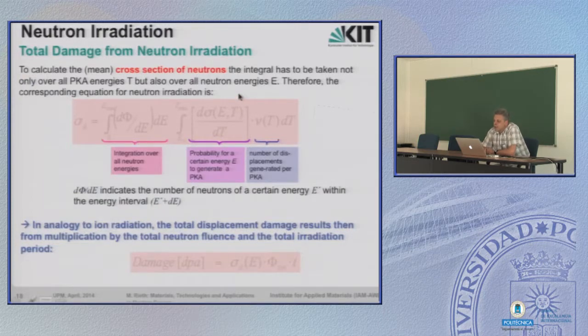It doesn't matter much for the calculation, because the cross-sections of these neutrons are calculated in the same way. We have also here the probability for a certain energy to generate a PKA. That's the same part as with the ion irradiations. Also the number of displacements generated by the primary knock-on atom. But then we additionally have to integrate over the whole energy spectrum of the neutrons. That's another cross-section given here. And in analogy to ion irradiation, this leads in the end to the same scheme for calculation of the damage in dpa units.